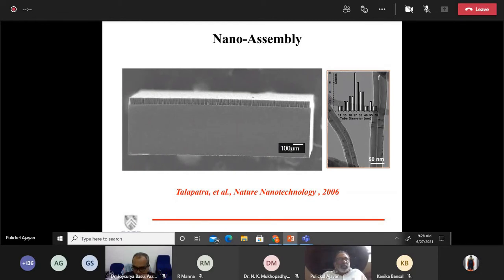So that's kind of the simplest way you can imagine a system which can be made from assembly of a large number of nanomaterials. It looks at a larger scale pretty uniform and with reasonable alignment, but as you go closer, you see this variation in particle size and structure and so on. In many ways, it's a little bit like the systems that nature builds. If you look closely at these bottom-up manufactured structures in nature, like the shell that I showed you, if you look closer and closer, there is going to be this intrinsic variability in terms of the platelet size, in terms of the thicknesses, and so on and so forth. But overall, the system has very interesting properties, and it behaves collectively quite well. And this is the same problem we see as you assemble things from the bottom up, and you are seeing this intrinsic variability in dimensions and structure.